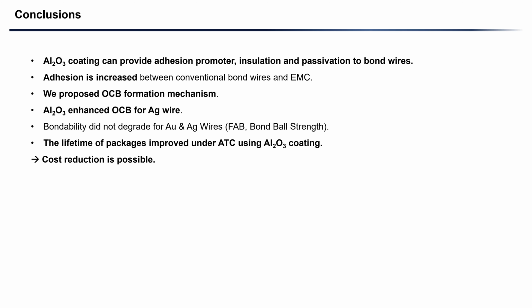For the conclusions, aluminum oxide coating can provide adhesion promoter, insulation, and passivation to conventional bond wires. Adhesion is increased by the introduction of aluminum oxide coating, and aluminum oxide coating enhanced OCB for the silver wire. I showed the same bondability, and the lifetime of the package improved during thermal cycles by making use of aluminum oxide coating. That indicates that we can decrease the diameter of the bond wire, and that a cost reduction is possible. Thank you very much for your attention.